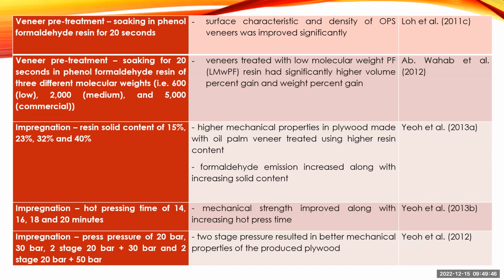Impregnation was also tested using different pressures of 20 bar, 30 bar, and different stages. They found that two-stage pressure resulted in better mechanical properties of the produced plywood. So this is some of the work that has been done on resin treatment of oil palm trunk veneer to improve plywood properties.